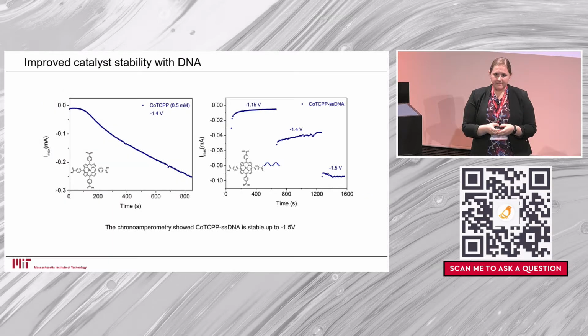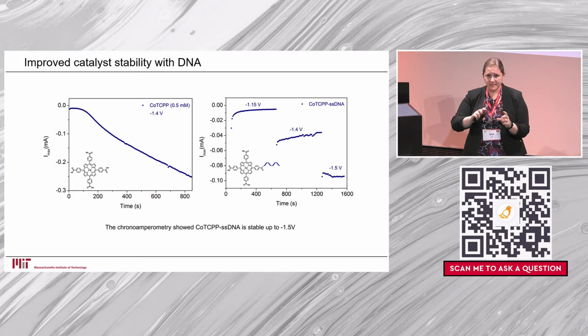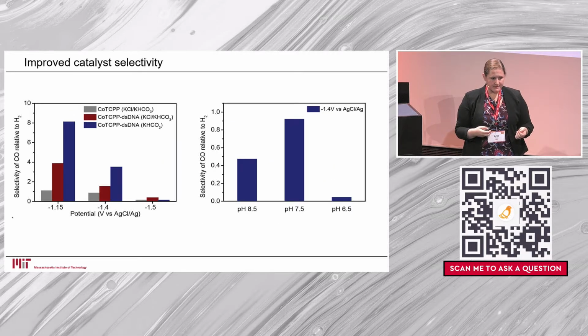And what we can see here is when we just add the DNA, so this isn't even on an electrode yet, we significantly improve the stability of these catalysts. So on the left, we see the free catalysts decrease in current, crapping out on our electrode. On the right, we see we can continually increase the potential we're using. So more and more power that would normally kill that catalyst, and it doesn't destroy the catalyst at all. So we've solved one of the core problems of these catalysts, their instability, by just adding the DNA in the first place. We can then look at these selectivities in different solutions.